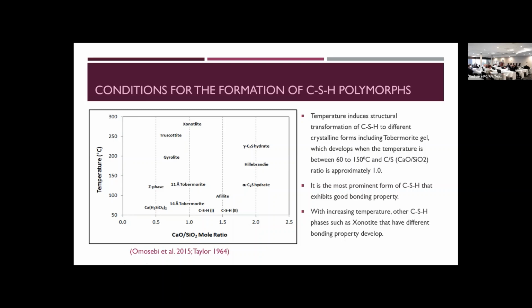Also, in order to identify what really happened in the C-S-H phase, we looked at the conditions for the formation of polymorphs. And in most of the cases, we came to the conclusion that it is the most prominent form of C-S-H that exhibits good bonding properties. If we can control some of these changes inside the cement, we probably will achieve better bonding by this development of the tobermorite gel inside the system.